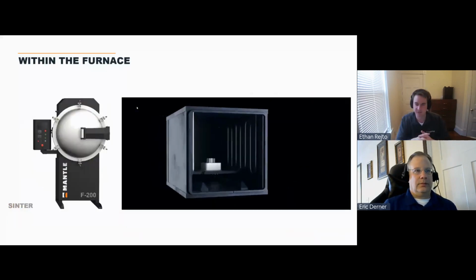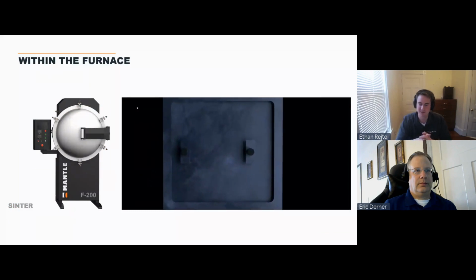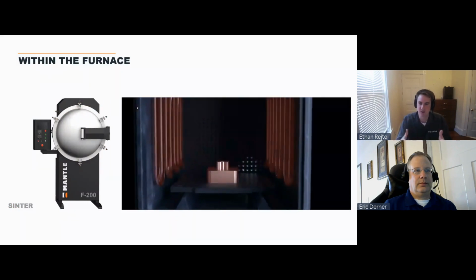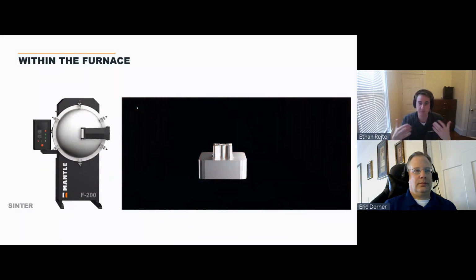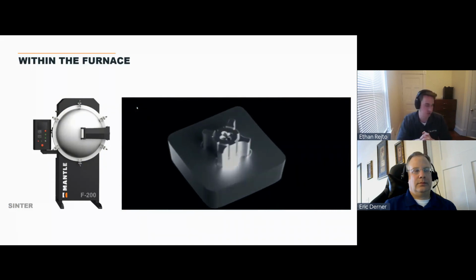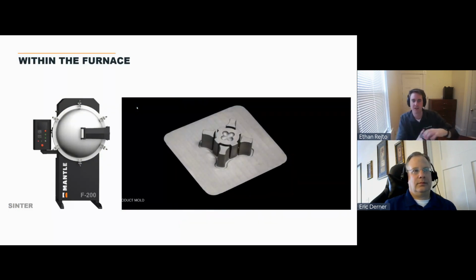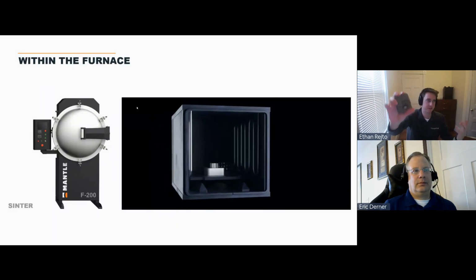Afterwards, apologize for the animation. It's a little harder to get a camera into a high temperature furnace, but you're going to put your part into the furnace. Again, batch process, so you can put a bunch of parts in here. That furnace is going to get just below the melting temperature of the material, and you're going to go ahead and sinter into a dense, strong metal part.